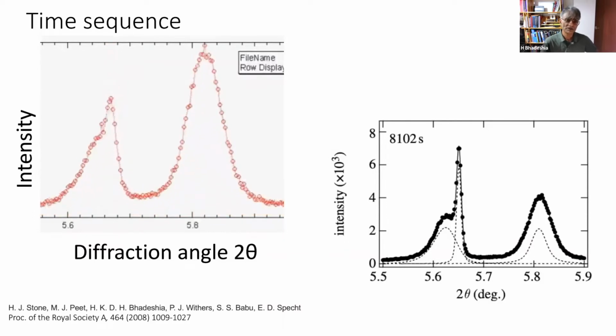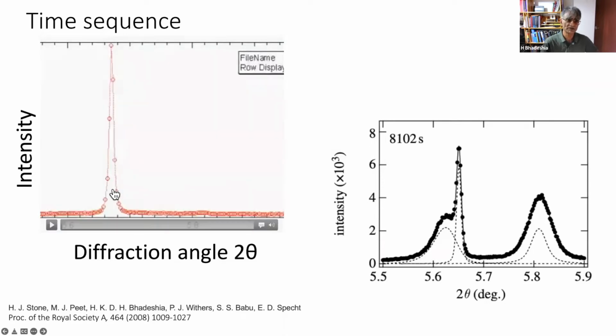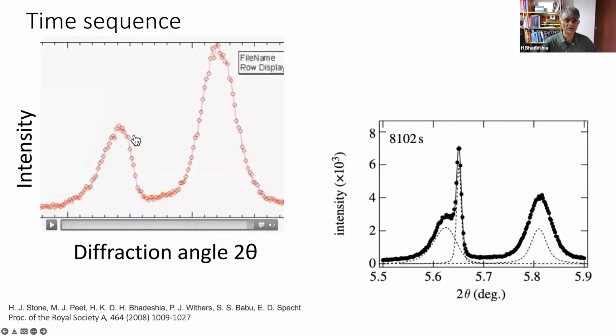So the thing that I want you to notice here is that this austenite peak here started off completely symmetrical, okay, but it ended up highly asymmetrical, indicating that it actually consists of two different peaks with different lattice parameters. Okay, this is the bainite peak, and this experiment was done at the Grenoble synchrotron. We first did it at the Advanced Photon Source in Argonne, but the resolution wasn't enough. We need high resolution for this experiment.